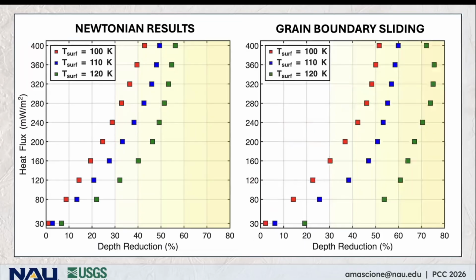Now, let's compare this to the results of our non-Newtonian simulations where grain boundary sliding was the dominant deformation mechanism. As expected, the GBS simulations allowed for more relaxation. This is because with a GBS rheology, viscosity decreases with increasing stress. So the highest stress regions of the crater would flow faster, unlike the uniform flow assumed under a Newtonian rheology.